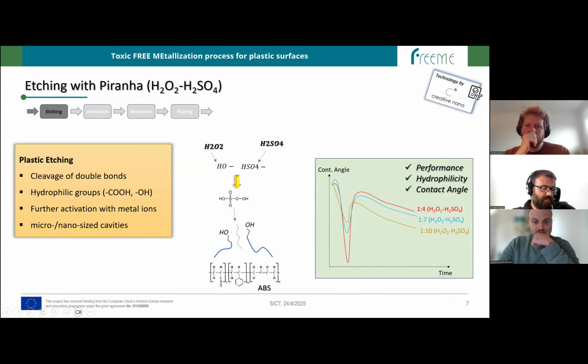I'm going to give you a very brief intro about each of these four steps proposed by FreeMe. So let's go to the first one, which is the etching by using Piranha, where actually sulfuric acid works as a carrier, taking the hydroxyl groups from the hydrogen peroxide, and then it cleaves the double bonds of the plastic polymers. And here in the case of FreeMe, we have ABS. And by this means hydrophilic groups, including carboxylic groups and hydroxyl groups, are formed on the surface.